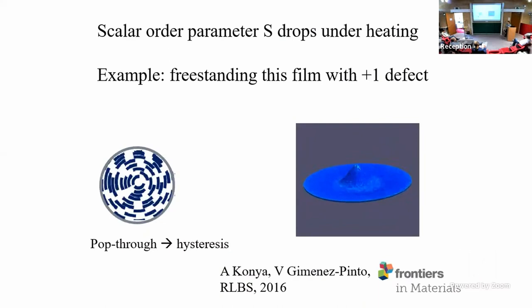Okay, now let's talk about liquid crystal elastomer. So I showed you the picture of a disk that turns into a cone. Here's a simulation of a disk turning into a cone. Because it has finite thickness, instead of going straight to a cone, first it becomes a hat with a brim, and then the brim pops through. So that's the effect of the non-zero